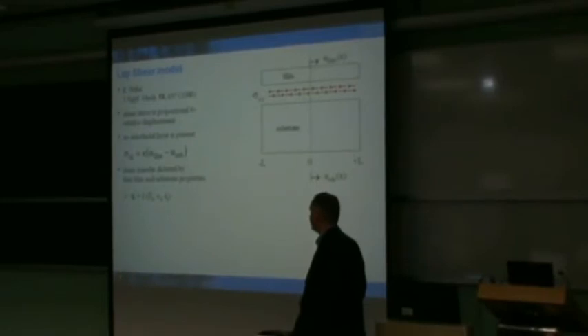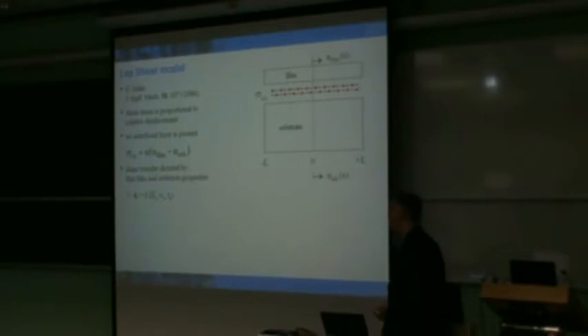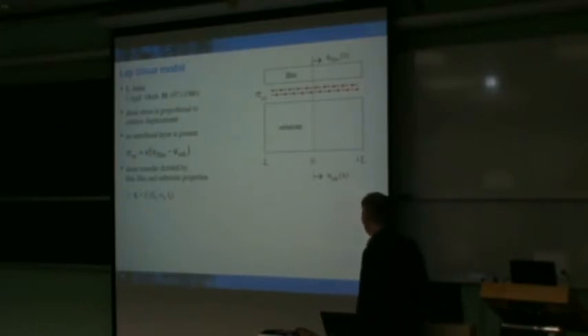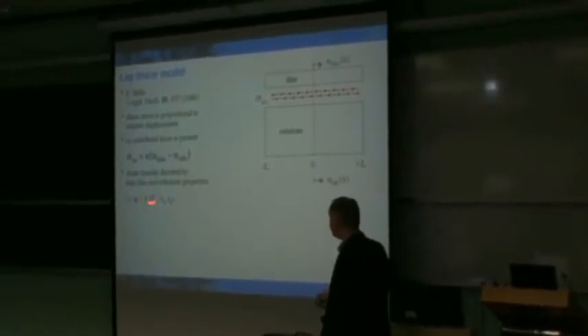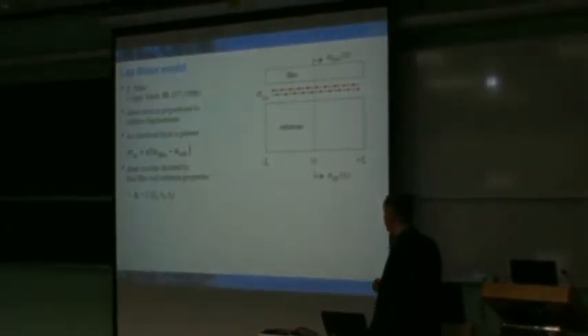Now, basically an analog to this type of technique was developed by E. Suhir, and you actually still see it implemented in much literature. I came across a paper this year, in fact, that incorporated it. And it's the same concept, that there is a shear stress here between the film and the substrate, and that will basically dictate the strain that's transferred between the two. The problem now is that you've removed that interfacial layer. And so you have another proportionality constant that's dependent on the elastic constants of the material as well as the thickness of those materials. And the shear transfer is dictated by them.